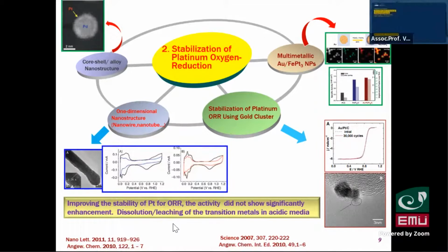So they try to enhance the ORR kinetics of the oxygen reduction reaction. They also get some good results, but there's a major problem with the difficulty of preparing this system, and also some dissolution of the second or third metal during fuel cell operation.